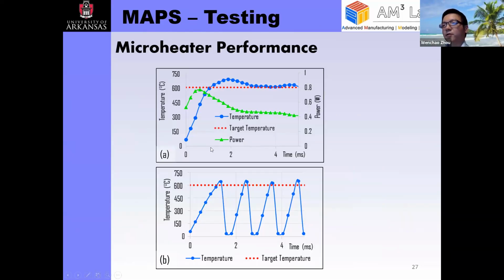As you can see, this is a test of single micro heater heating, and this is the time axis. It's in millisecond time scale, and this is the temperature. Our target temperature is 600 C. As we can see here, the temperature goes up, overshoots a little bit, and then the closed loop control kicks in and brings it back to 600 C in a few milliseconds. And the power consumption, which is the green line here, can maintain the 600 C temperature at 400 milliwatts here.